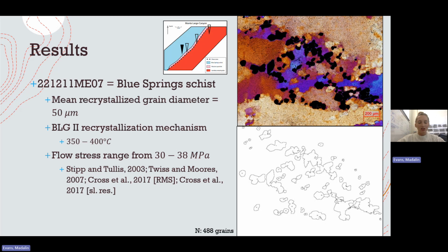The petrographic observations are consistent with a bulging recrystallization mechanism, and I know that I had only gone over a bulging recrystallization mechanism specifically, but the porphyroclasts in this sample are mostly surrounded by recrystallized grains, and that is indicative of a bulging regime. And in nature, that has a temperature range between 350 to 400 degrees Celsius.